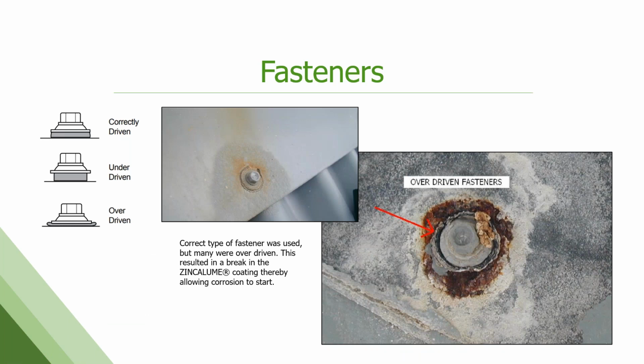Fasteners. This is an example of what can happen with an installer who's being a little careless or doesn't know what they're doing: if you overdrive these fasteners down through the metallic coating and into the base steel, now you have an opening where water and moisture can get in, and you're going to get red rust. Now, it presents very similar to the picture before, which is galvanic corrosion, right? The paint is bubbling up, but the mechanism is a little bit different. It's because they broke through the coating.